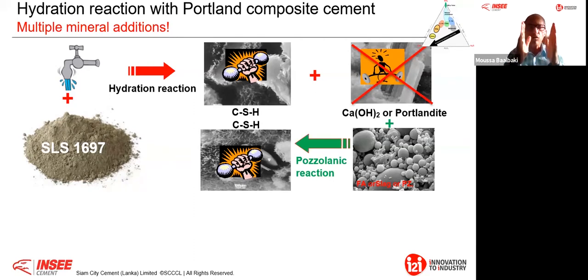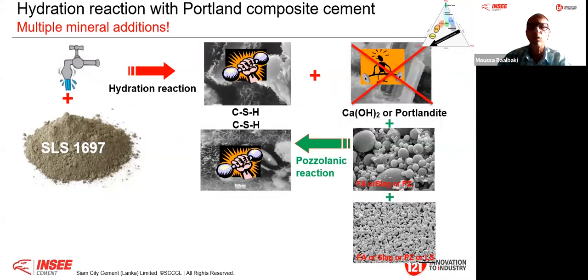If I look at OPC, I look at Portland limestone cement, I look at blended hydraulic cement, the second constituent, for example, in Portland limestone cement, I can put slag or fly ash, but it's minor, less than 5%. If I go to blended hydraulic cement, like fly ash cement, I can put limestone, or I can put fly ash, but this is minor, it's below 5%. They are not main constituents. But in the Portland composite cement, they become main constituents. Therefore, if I add high-grade calcium carbonate to the slag, or I add fly ash to the limestone, to the high-grade calcium carbonate, I have a third reaction that will take place.